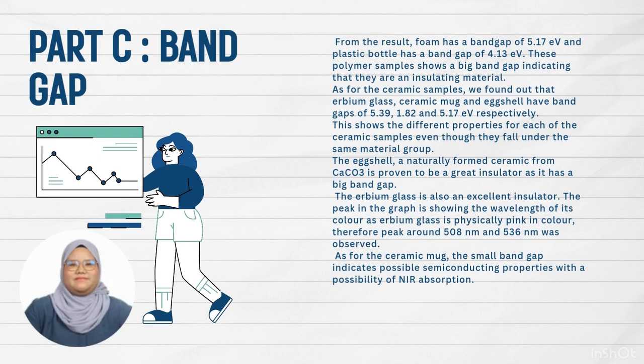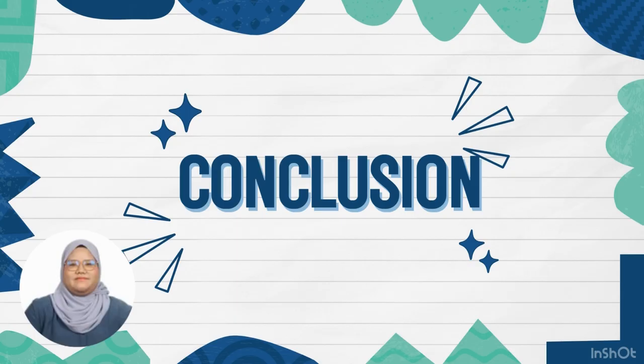The peak in the graph is showing the wavelength of its color, as erbium glass is physically pink in color, therefore peak around 508 nanometer and 536 nanometer was observed. As for ceramic mug, the small band gap possibly indicates semiconducting property with a possible NIR absorption. Now we are moving from discussion to the conclusion part.